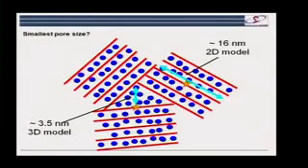Okay? Now, something being quite long either says these two types of pore have to be quite a long distance apart, or there has to be some other reason why the exchange between the two of them is quite long. And we couldn't think of any sensible theory as to why two types of pore should be quite large distances apart. So the model we now really think is probably closest to the truth is that one of these types of pores is water in the interlayer, and the other type is then these pockets between these different nanocrystalline regions.